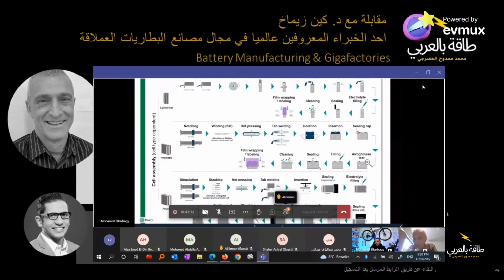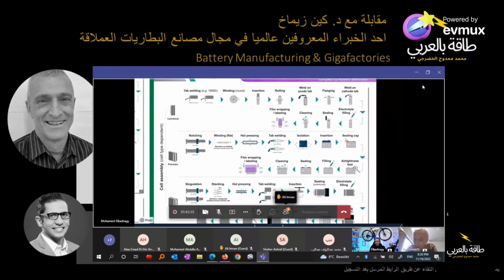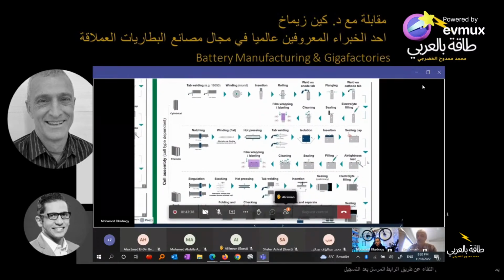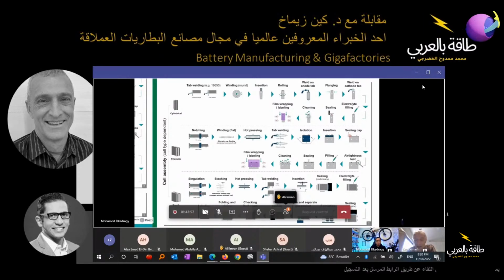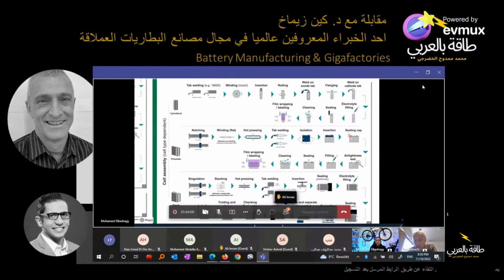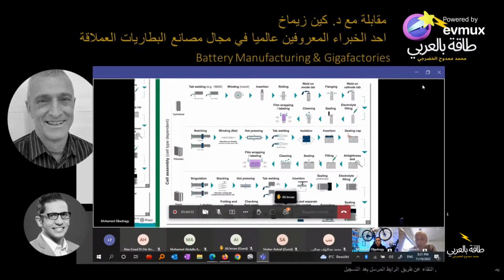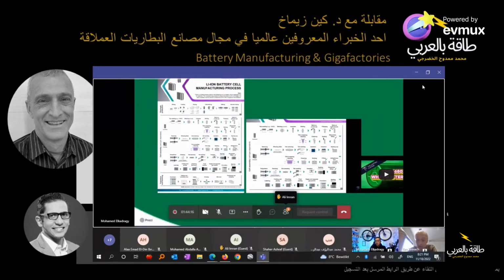This is not like soaking water into a sponge, which, by the way, also takes time. But imagine that you have a giant sponge in a package and you put some water in one part, it's going to take time to soak through. And until it soaks through, you have 2 problems. One, you can't get your electrolyte in. You can't get enough electrolyte in because you need to get in a certain amount. And the other problem, so sometimes electrolyte filling can take 30 minutes. Okay, and you pull a vacuum, and then you put pressure, and you pull a vacuum, and you put pressure, and you pull a vacuum, and you put pressure. But remember, electrolyte is flammable, it's toxic, it's hazardous, and it can't be exposed to water.